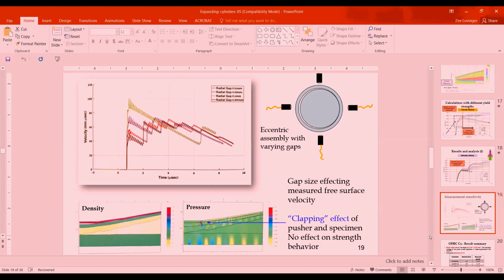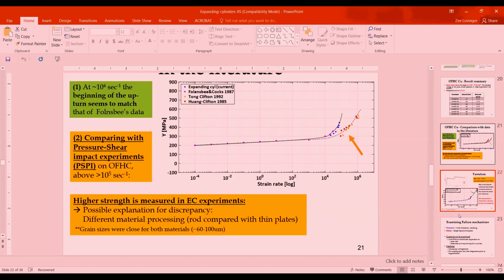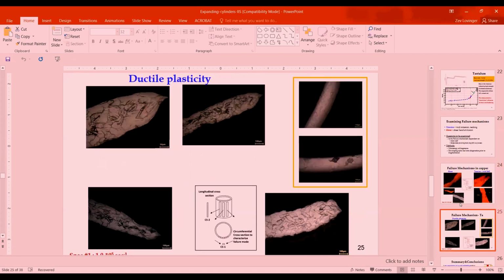If you could just elaborate on that a bit. I mean, we characterize the initial microstructure, like the grain size, like you could see here for tantalum, for instance. We don't see any changes in the size or refinement of it. And you could see here on the order of 5 to 6 grains across the thickness. This is only 250 micrometers, like a quarter of a millimeter. So we're getting about 5 to 6 grains, but we didn't see any evolution of the grain size under these experiments.